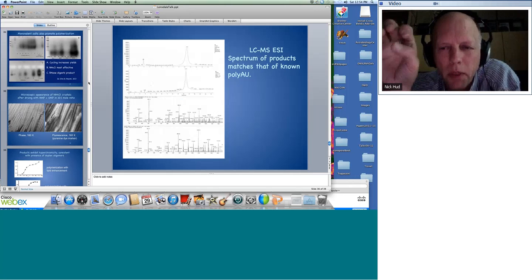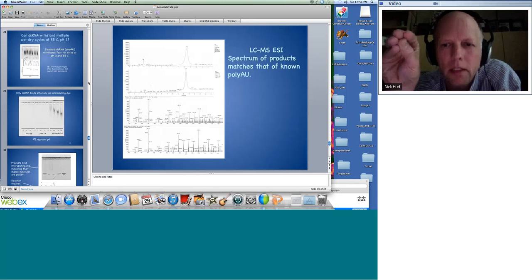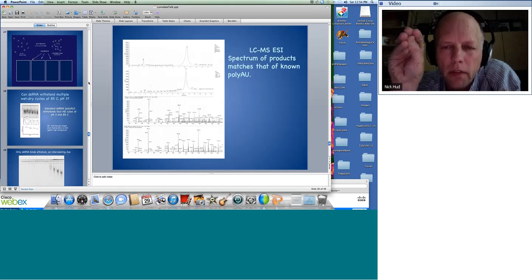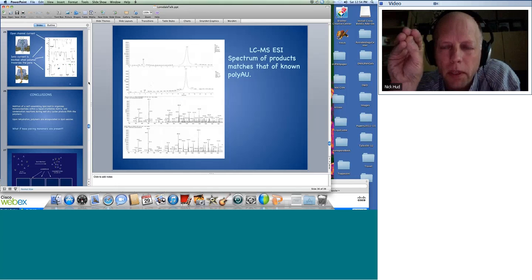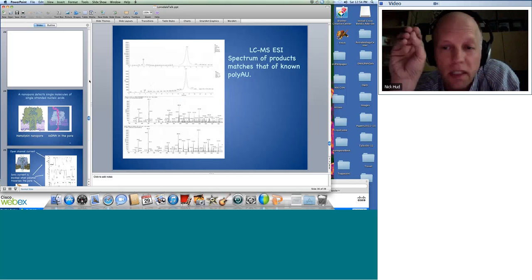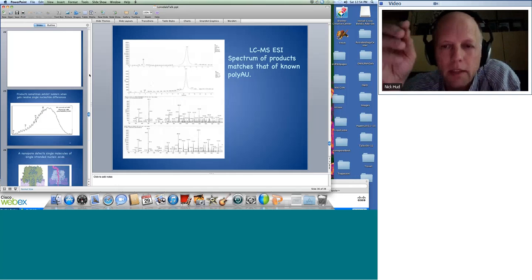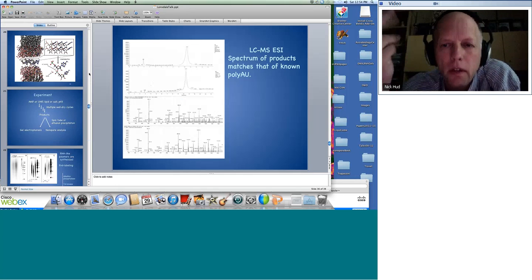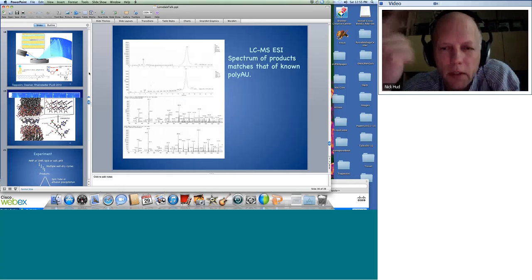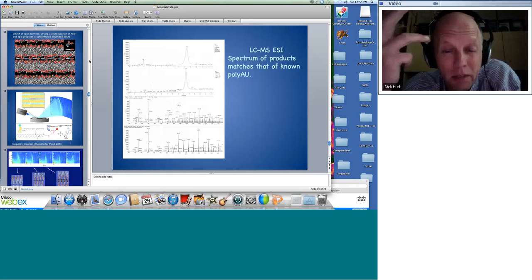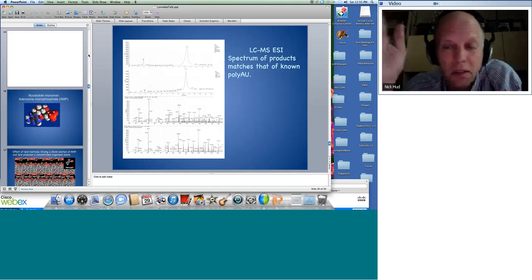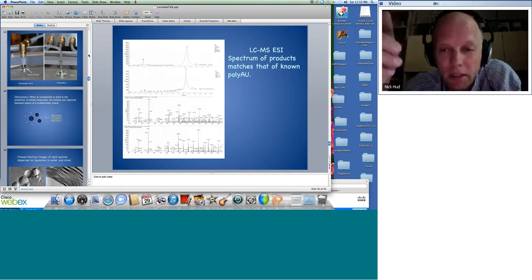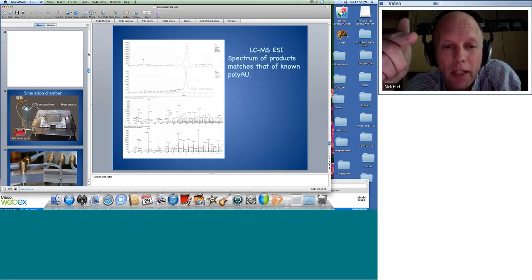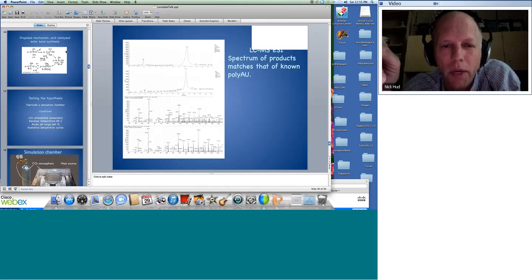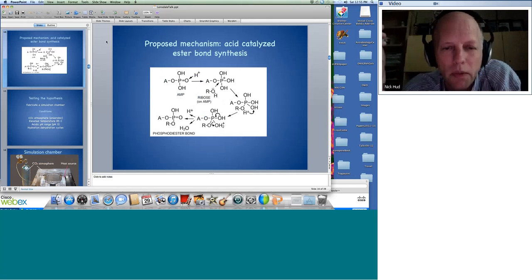Matt's saying that you have the ammonium ion come in, which, in addition, we also know that of the different cation species, ammonium has probably the highest affinity for phosphate groups, so it's going to stick there. And I think what Matt's saying is that the proton would come off and go onto the phosphate. Ron could correct me on the mechanism, but I think you're going to have your ammonia add, going through that pathway, and then lose your ammonia later when it reacts further. Is that what you're talking about, Matt?